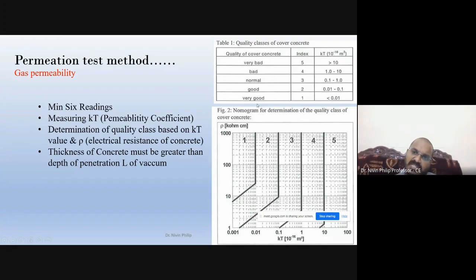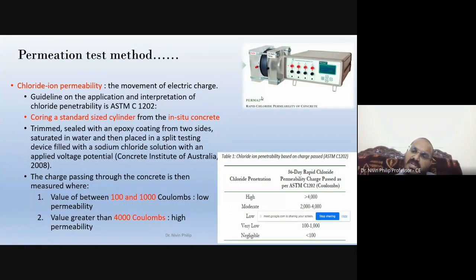Next is the chloride penetration method. When a structure has deteriorated, we take samples of 100 mm dia by 50 mm. Then we go for a rapid chloride penetration test. One side is filled with sodium hydroxide, and the other side is filled with sodium chloride. We apply some voltage and try to transfer the chloride ions from one side to the NaOH side. We monitor how much chloride ion is transferred over around 6 hours. From that value, we identify how much the permeability is.